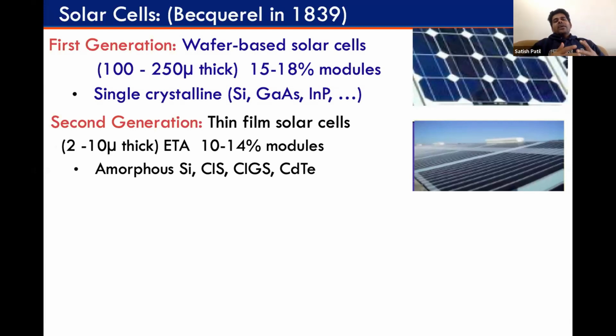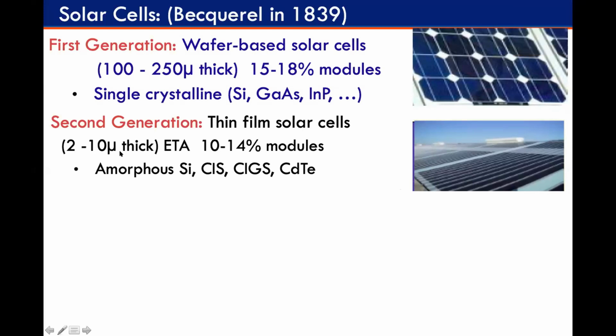So, and then it has, and it's a very rigid material, like a glass. So essentially, to address some of these questions with the silicon, second generation solar cells came into the picture, and then people did thin film solar cells. You see that now the material quantity becomes 2 to 10. The thickness of the layer is 2 to 10 micrometers thick, and the efficiencies are 10 to 14%.